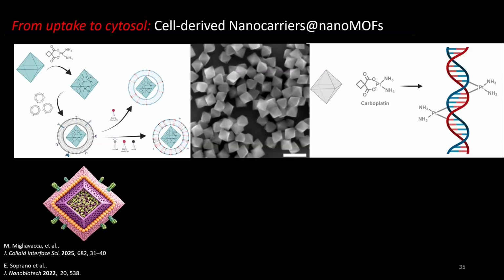We remove the membranes, and then we make nanoparticles. So now we want, instead of putting cell-penetrating nucleic chemistry, to coat the MOF with these cell membranes, because there is something very interesting for me called homotypic targeting. If you make nanoparticles of one specific cell type, if you work with cancer cell lines, you make it from HeLa, or another one, and then you add it to different cancer cells, it always goes to the cells from which they originated. It's called homotypic targeting.